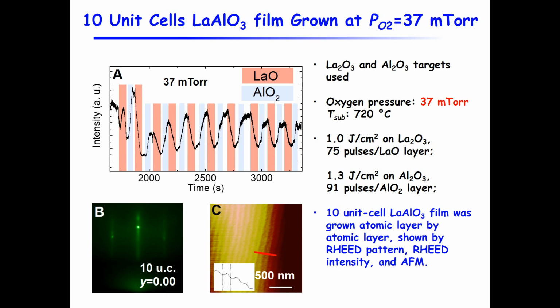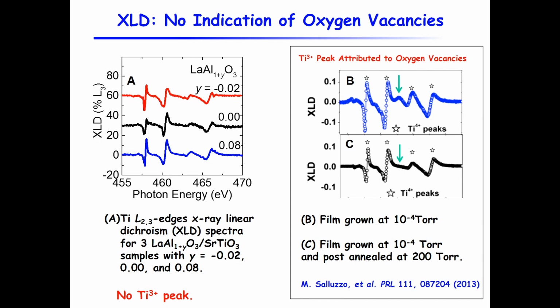So basically, what I'm showing here is that we could grow layer by layer at this very high oxygen pressure that nobody else could do. And the consequence is that we think this condition allows us to grow these interfaces without oxygen vacancy. Well, I cannot say without oxygen vacancy. I can say that it is much better oxygenated compared to people who grow the film at low oxygen pressure. And there's no good way to measure oxygen vacancies.